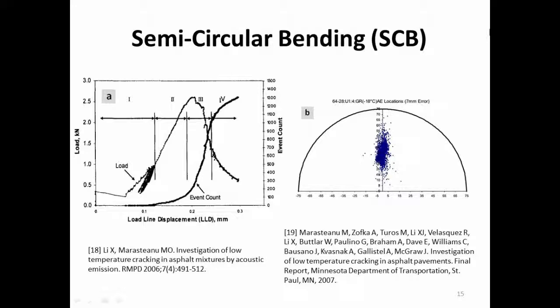And then they analyze these count versus load curves. They divide the load curve into 4 stages. In stage 1, it's almost linear elastic. You can do loading and come back to the same place. For the second stage, you go from the end of the linear elasticity to the peak load, and in this period the inelastic behaviors occur more and more evidently. In the third stage, it deviates from the peak load down to maybe half or 60% of the peak load. In this area, if you check the counts, you see a significant event count occurs. That means a lot of micro cracking happens at that time. And finally, for this part, even when you go past this point, the count still increases, but the load decreases so much that the material basically loses its properties.